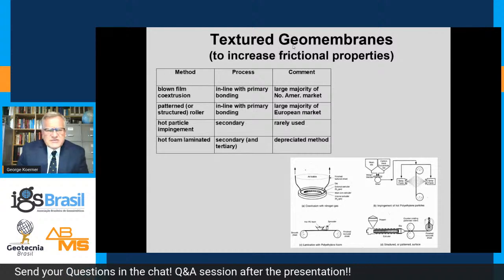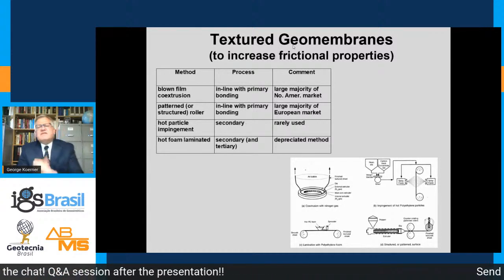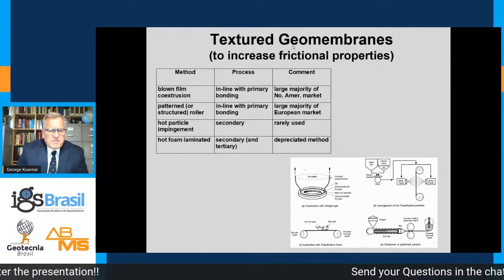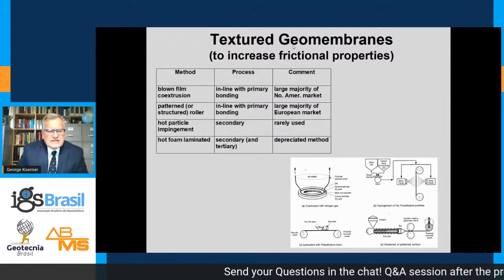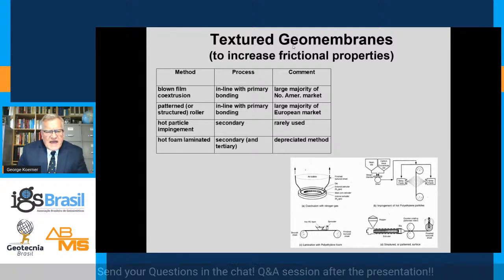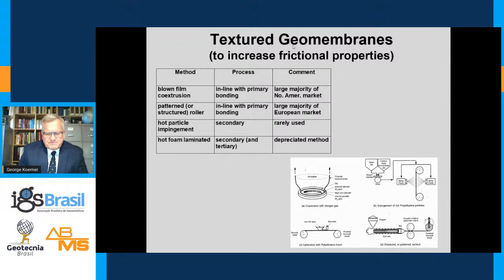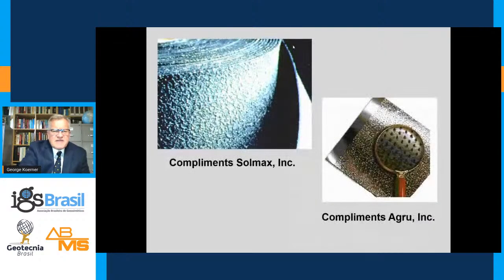As far as texturing material, you have 4 different methods to texture. For blown film, it's typically a nitrogen expulsion. You can have a patterned roller for the die cast. Hot particle impingement: I've seen that in Chile as well as China and Europe as well. Hot foam lamination I see less and less of. That was a favorite of a manufacturer here in the United States, but we see less of that process.